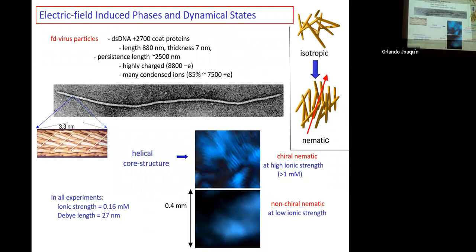So now I'm going to talk about rod-like colloid particles which are highly charged. We take a virus particle as a model system for rod-like charged colloid particles. These are rod-like particles about a micron in length, with a thickness of about 7 nanometers, so they're very long and thin. The persistence length is 2.5 times the contour length, so they are pretty stiff - they typically bend a little but not much. So it's a good model system for a rod-like colloid.